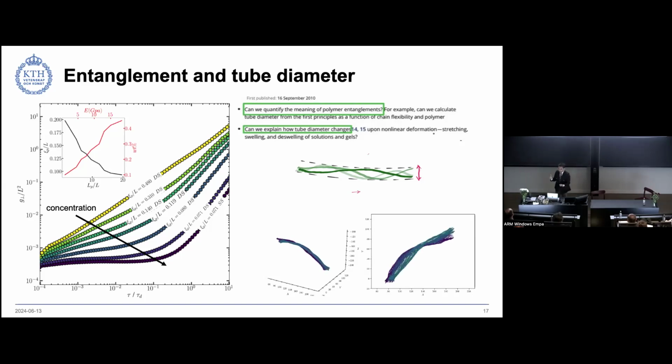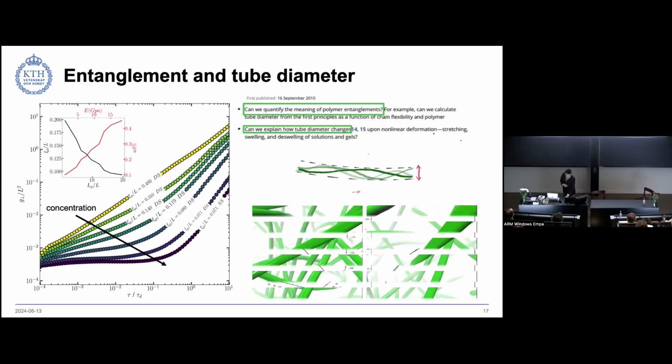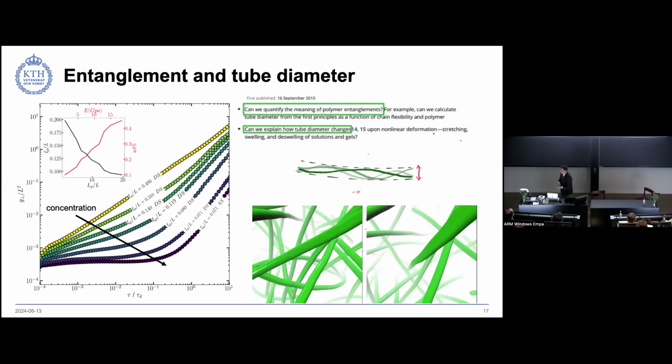And with the help of this, we can also quantify the onset of entanglement. So between linear and plateau, we find the point or the case that it starts the beginning of the tubing effect. And if we do this for many cases, we come up with the inset image here. The image tells us that, okay, if we have two samples of polymer or cellulose nanofiber